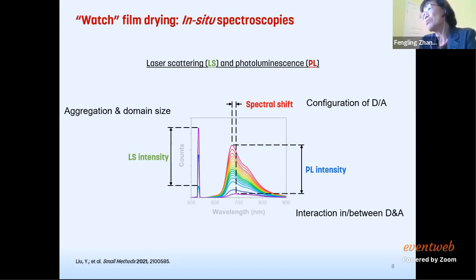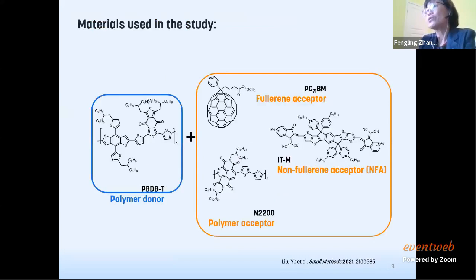So with this, we need a system to work with. Then we chose the materials used in the study. We fix the donor and vary the acceptor. We select three different representative acceptors. The traditional fullerene acceptor is not so popular now, because we have the new non-fullerene acceptors with better absorption compared with the fullerene acceptor. We also have a polymer acceptor. Polymer acceptors nowadays are also not as efficient as small molecule non-fullerene acceptors, but they have a big difference: the molecular weight. So we want to know how the molecular weight and the molecular structure influence the film drying.